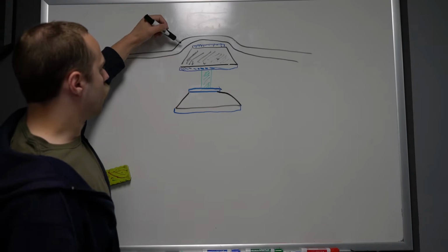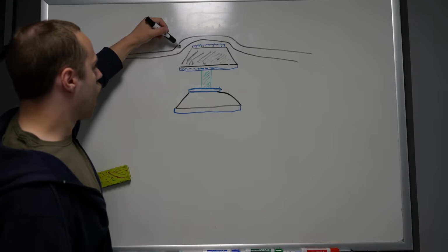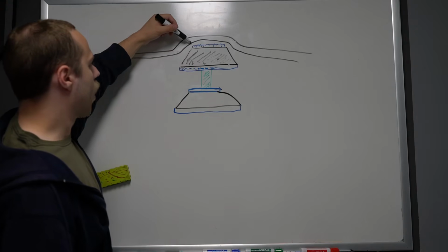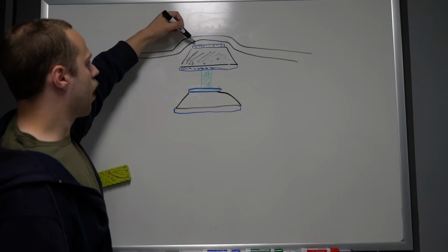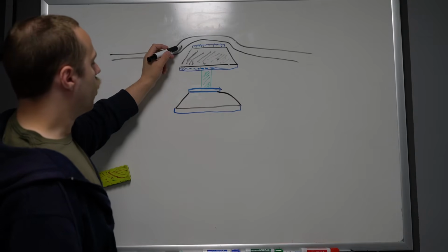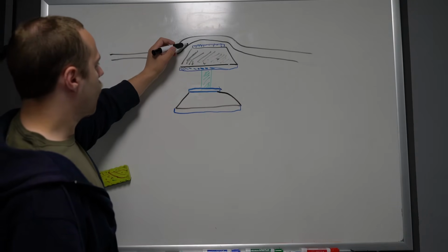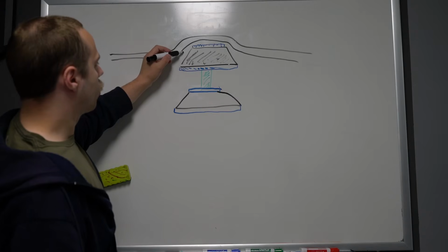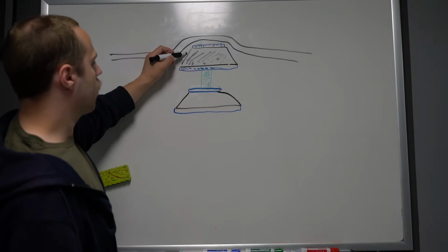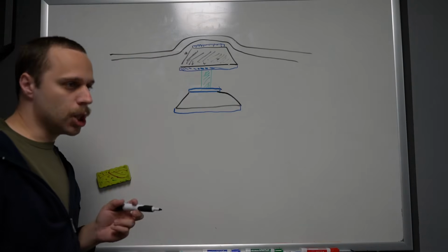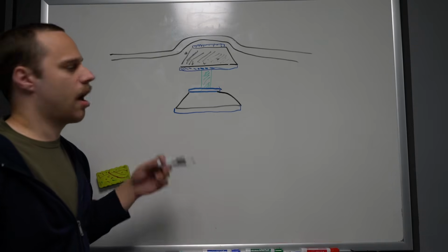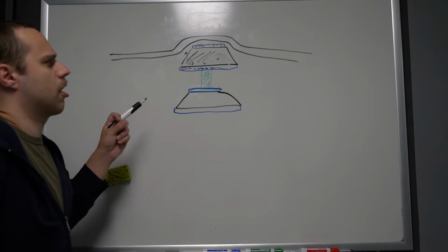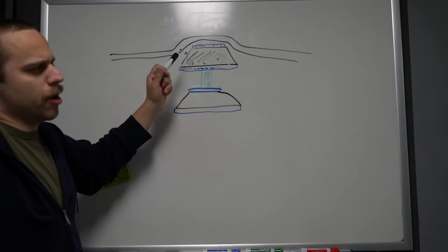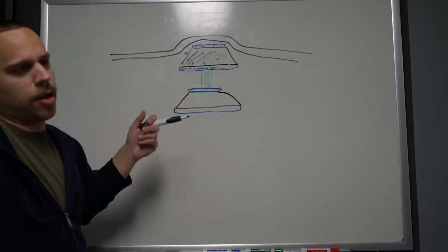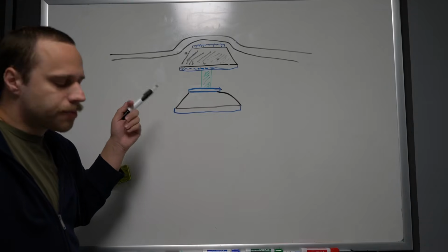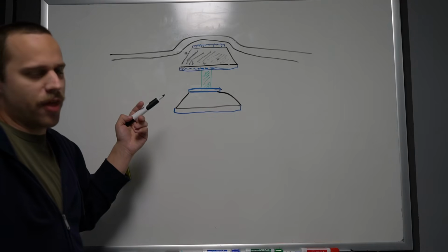So again, there's usually going to be a thin area on the edge, right where there are the humps over these metal layers. So we will start to get some HF coming in, thinning out the dielectric, and eventually it's going to start hitting the side of the aluminum. And HF will also eat the aluminum. We'll get aluminum fluoride and probably some other reaction products, because the aluminum is not pure aluminum. It's usually got a little bit of silicon or some other materials alloyed in with it.